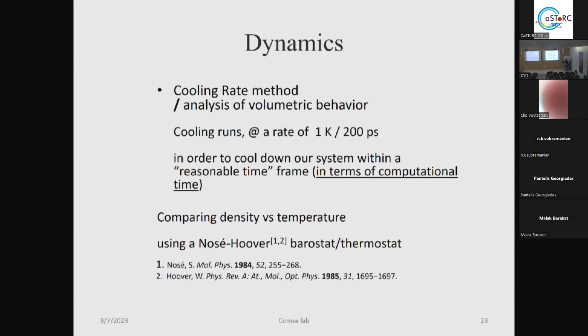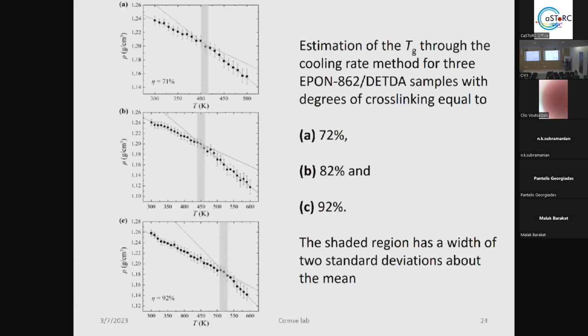So in order to have reasonable times, we used that cooling rate, and compared, of course, the density versus temperature after that. We can see here the three different plots for the three different systems, and we can see the change of the slope here with the shaded region, the width of two standard deviations.